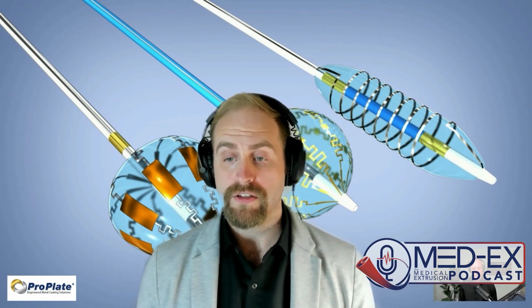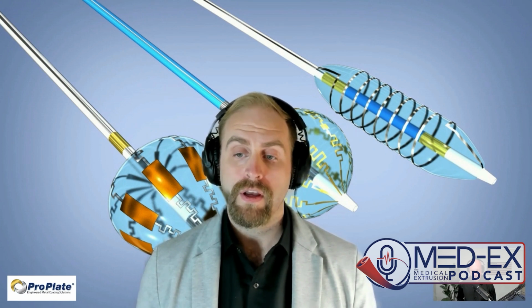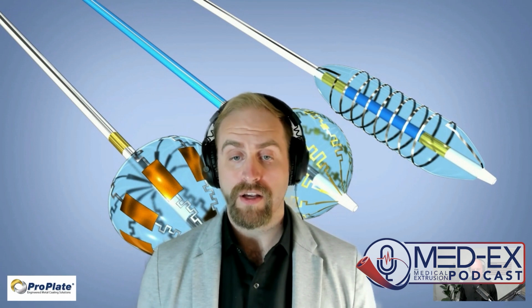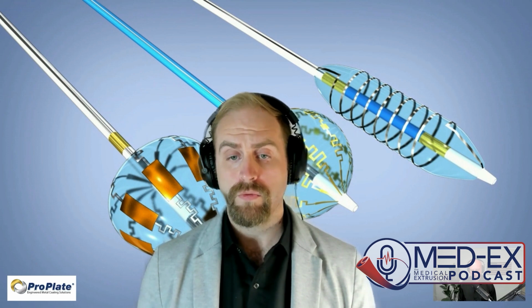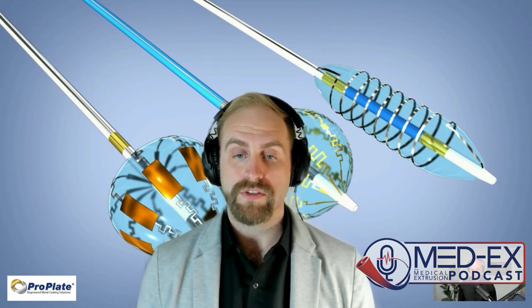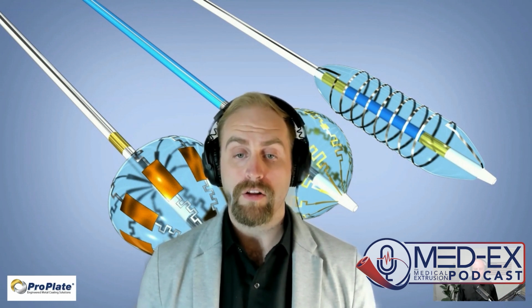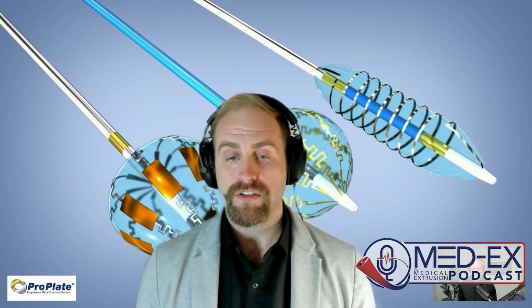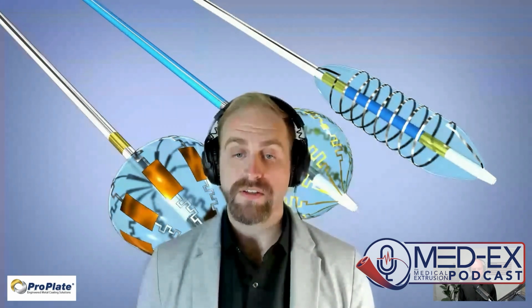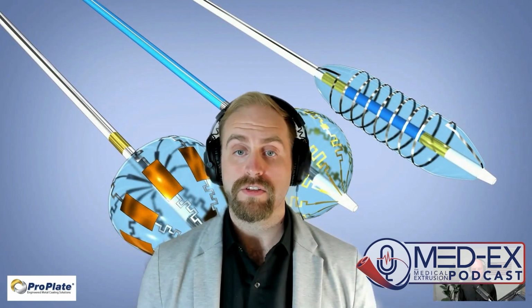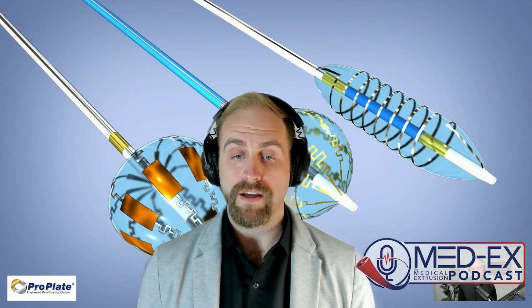Sure. So what we do is we'll take, like you mentioned, a hypotube, stent, or similar component that might need a marker band or even a ring electrode on it. From there, we'll apply a liquid polymer to it, and that acts as the masking. And then we'll move into a laser ablation process that selectively removes the areas of the component that we want to expose for the plating process. So we'll have a bare metal surface in those areas. Then we can move to the plating process, which involves a series of activation and cleaning steps, followed by the actual plating step itself. Those activation and cleaning steps simply remove any residue that's left on the parts, and they'll actually activate the surface as well to create free radicals for bonding and promote adhesion.